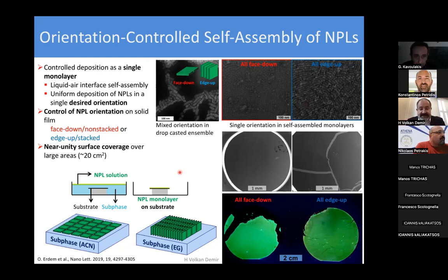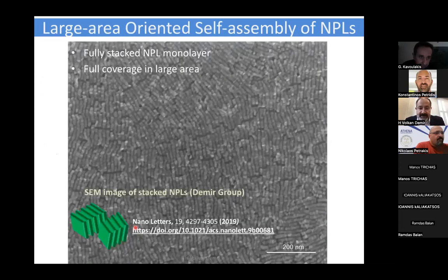And what we found is using a specific subphase, we can favor the orientation of these nanoplatelets at the interface, face down or edge up, a single phase. And then simply draining out the subphase, we can essentially work with any substrate. This already aligned monolayer of nanoplatelets would simply sink in onto these structures. And this is one example where we very densely edge up, stack these nanoplatelets.